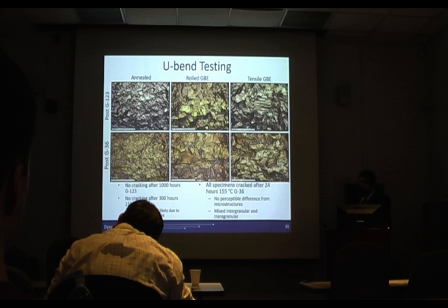Our curved sigma 3 grain boundary still resisted cracking. Basically, you end up with facets that do not corrode. And about half of the sigma 3 grain boundaries encountered had corroded and uncorroded facets. The crack arrests are more similar in size to twin-related domains. They weren't identical in this work, but were limited by our field of view using the technique that we did.